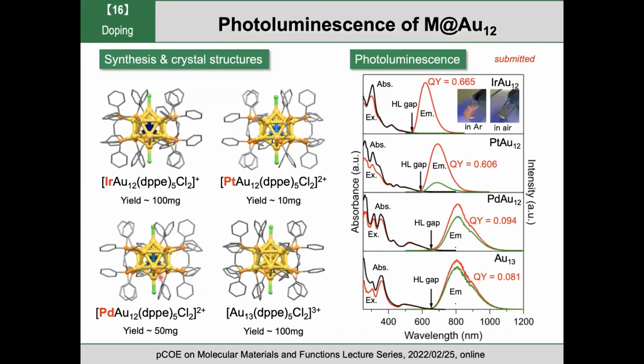And we expanded this study, and we are now conducting a systematic study. Here is an example. We can successfully dope a single iridium, platinum, or palladium atom at the center of the gold-13 core. And we see intense luminescence. And again, the quantum yield is nearly 70% in the case of iridium doping. And this is almost completely quenched by oxygen. So this is assigned as phosphorescence. So we are now studying the photophysical properties of doped gold-13 superatoms.